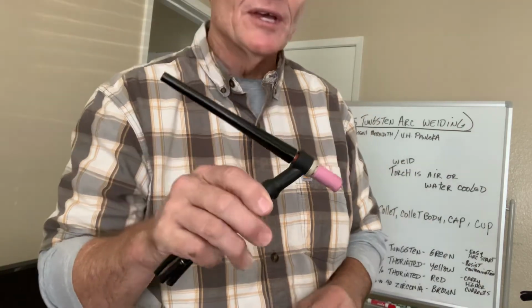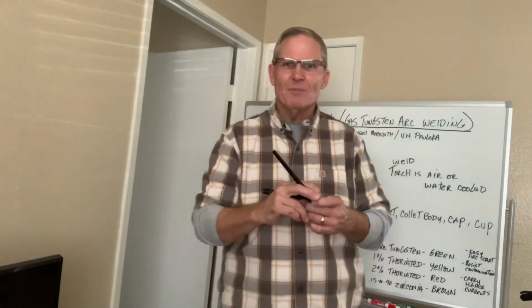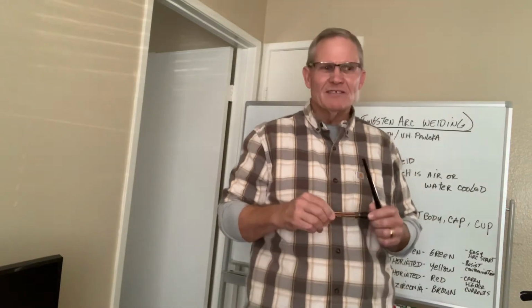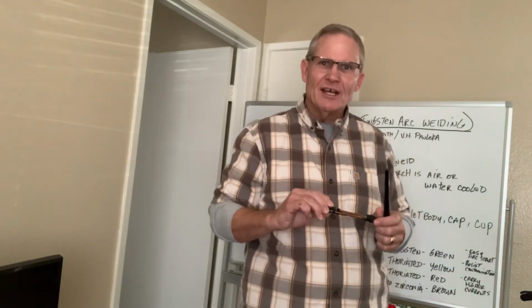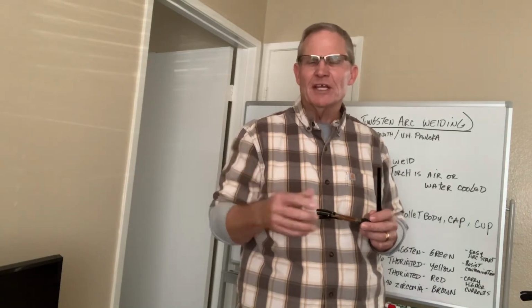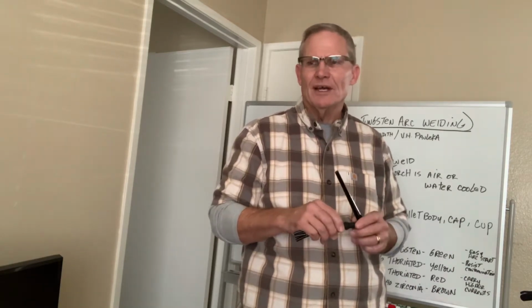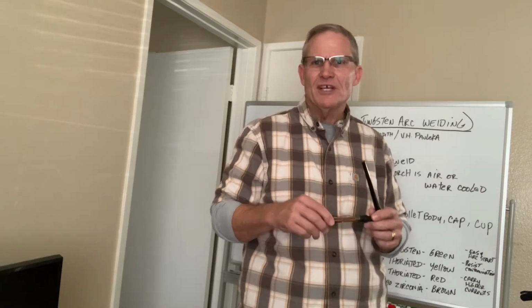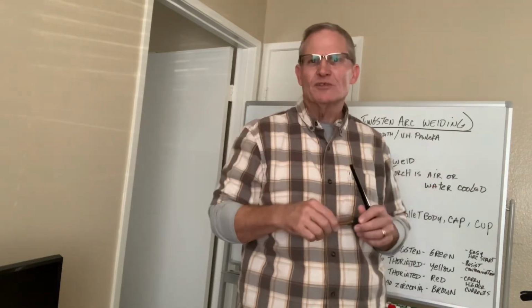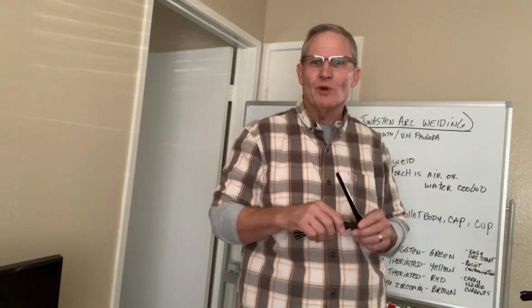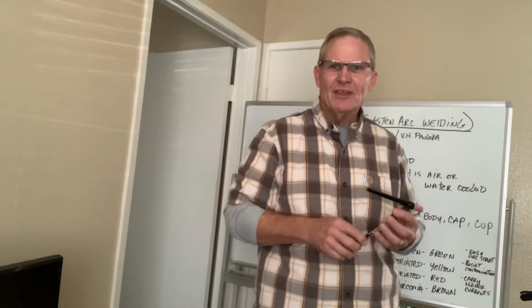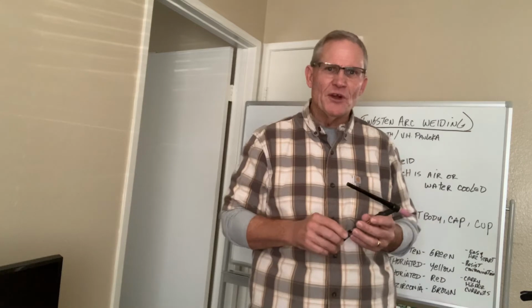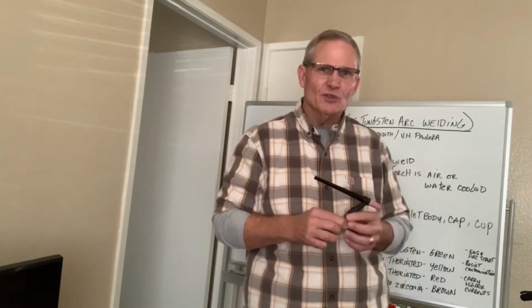But what's really nice about this weld process is that it's very precise, very concentrated type of welding. We certainly weld a lot of aluminum and stainless and Monels and the Inconels. It's used quite a bit in the aerospace industry, but also throughout the welding industry itself. Once you use the process, you see the advantage of it, particularly with thinner metals and how well you can control the heat during the welding with it.